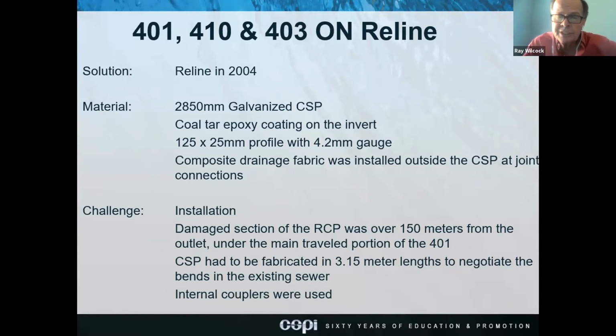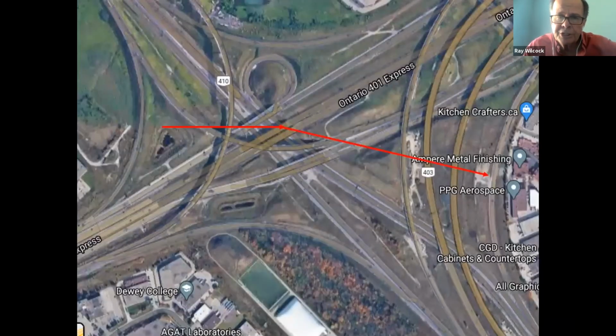The challenge was installation because there was a damaged section. The damaged section of the RCP was over 150 meters from the outlet under the main travel portion of the 401. So we had to fabricate the CSP in 3.15 meter lengths to negotiate the bends in the existing sewer. And we used internal couplers as I showed before. Again, I just wanted to show you there was a bend there. So when those CSP pipes were being pushed through, we had to get them around that bend. And it was very tricky and very difficult.